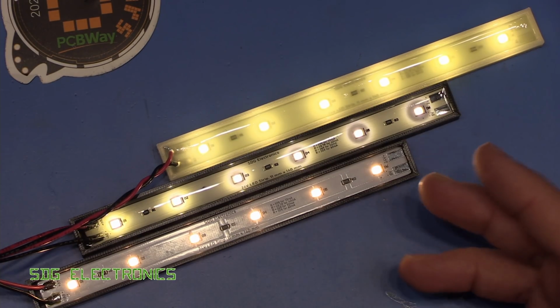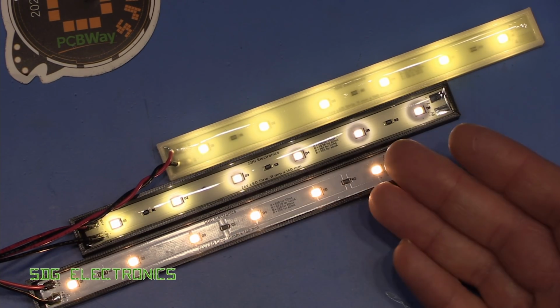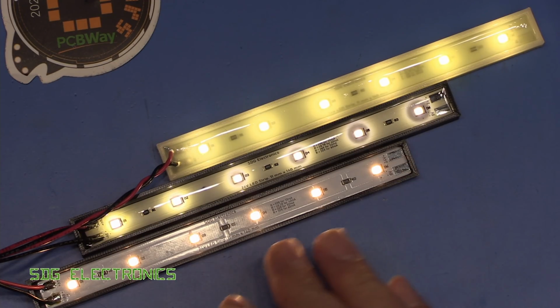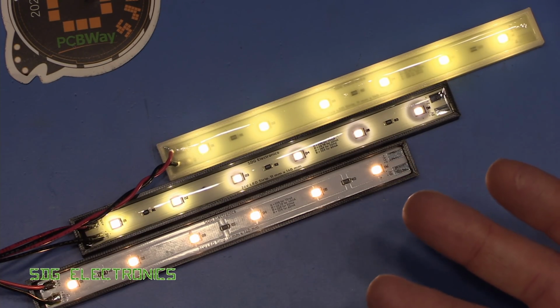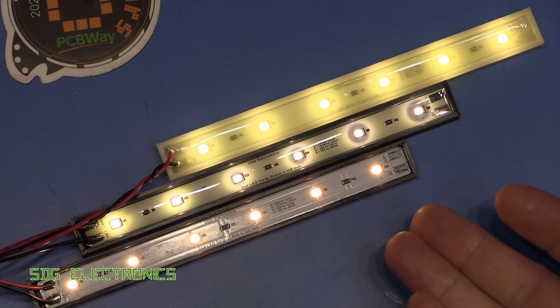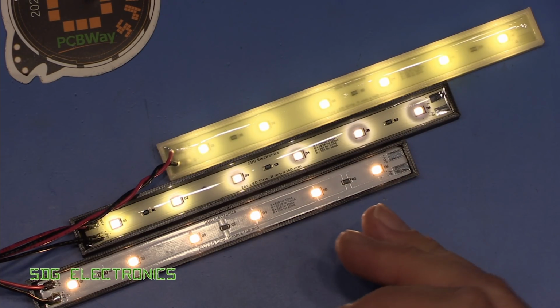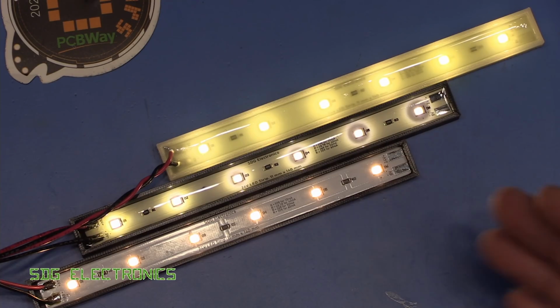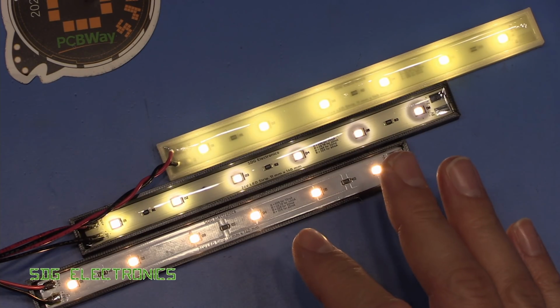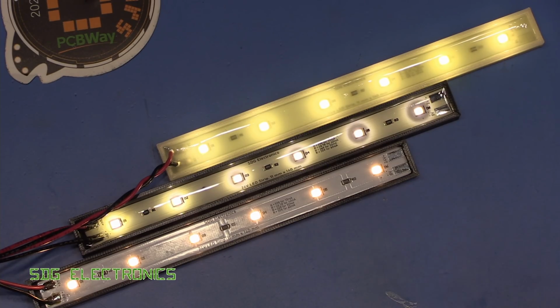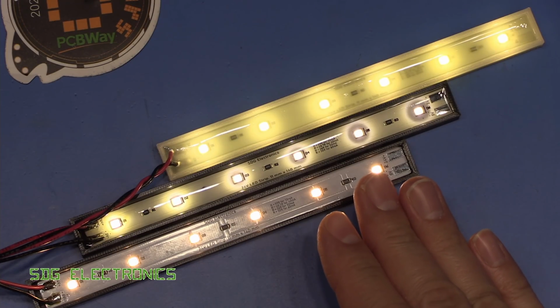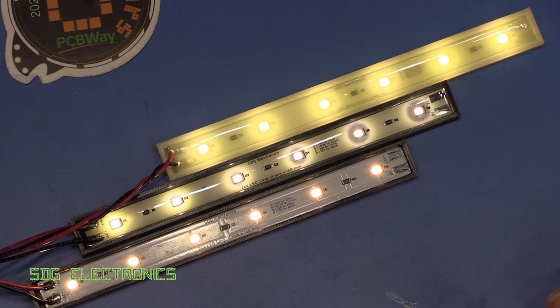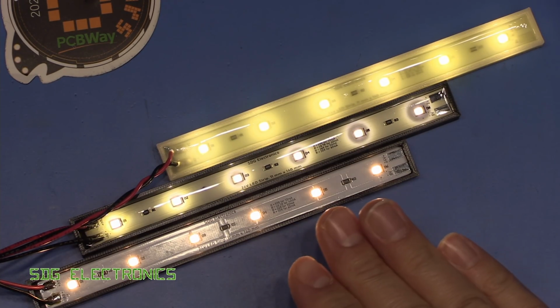So some interesting results there, and I think what we can learn from that is if you do need to encapsulate your LEDs, either for waterproofing or to reduce the amount of dust getting onto your PCB or just to increase the toughness of your PCB, then you should try and keep the thickness of the resin as thin as possible, because firstly, the resin is not 100% optically clear, and what that means is that it is going to absorb some of the light from the LEDs and decrease the efficiency of your LED application. But also, the thicker the application of resin, the more we're going to see a color shift towards the cooler color temperatures, which in most cases is probably going to be undesirable. So you do want to keep them as thin as possible.